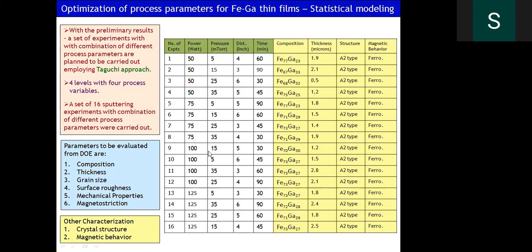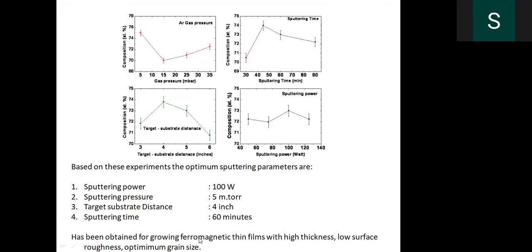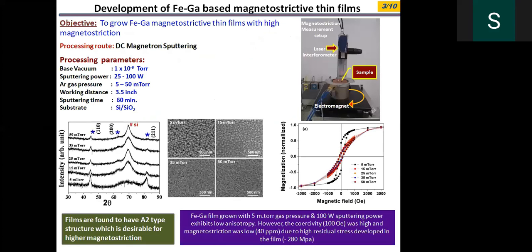Based on the design of experiments we carried out, we are interested to see different parameters like composition, thickness, grain size, surface roughness, mechanical properties, and magnetostriction. From this design of experiments, we could see the optimized parameters: the sputtering power, pressure, target to substrate distance, and the sputtering time. These are the optimized parameters we have calculated based on the different experiments. We have also tried to measure the effect by looking at the microstructure and X-ray diffraction studies.